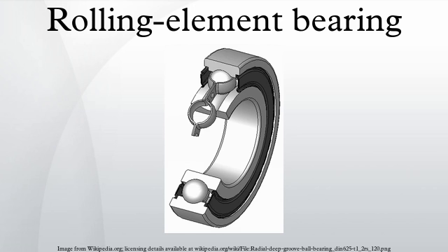The operating environment and service needs are also important design considerations. Some bearing assemblies require routine addition of lubricants, while others are factory sealed, requiring no further maintenance for the life of the mechanical assembly. Although seals are appealing, they increase friction, and in a permanently sealed bearing the lubricant may become contaminated by hard particles, such as steel chips from the race or bearing, sand, or grit that gets past the seal. Contamination in the lubricant is abrasive and greatly reduces the operating life of the bearing assembly.